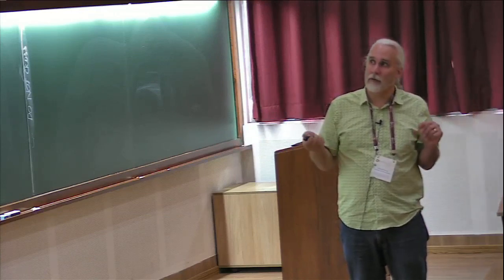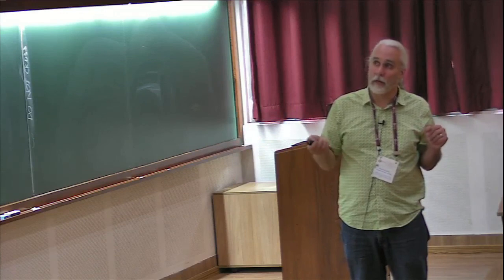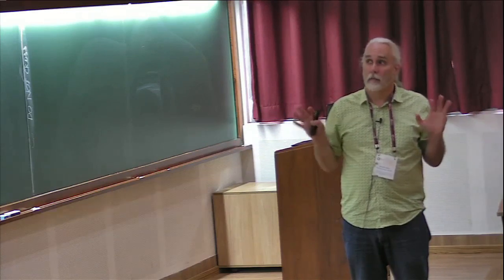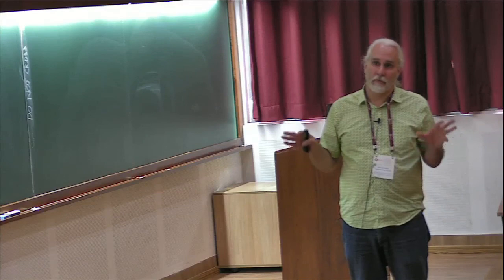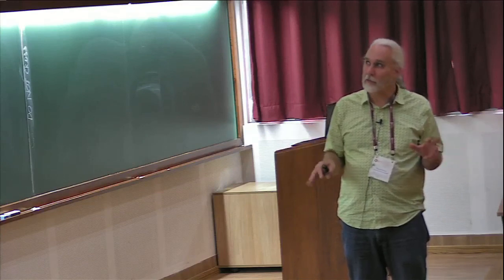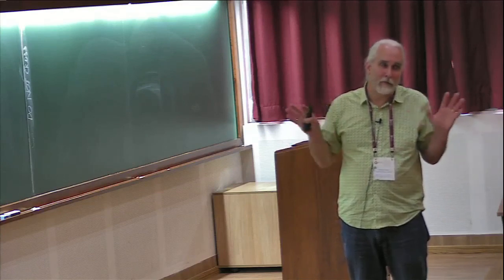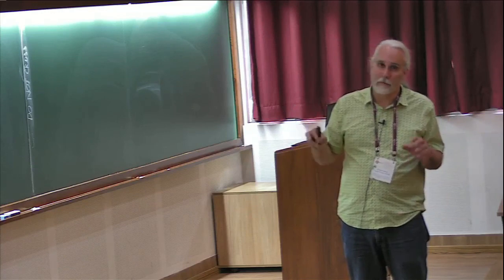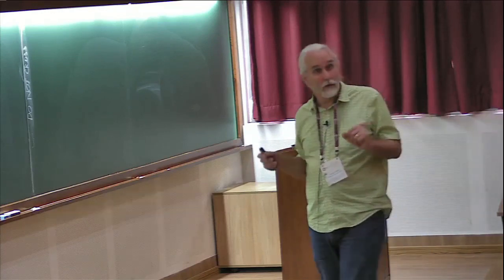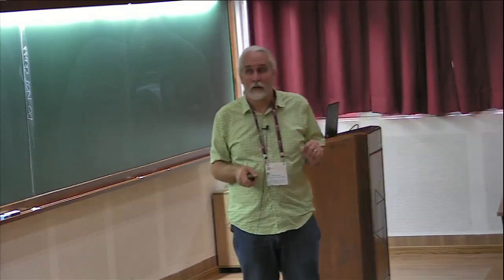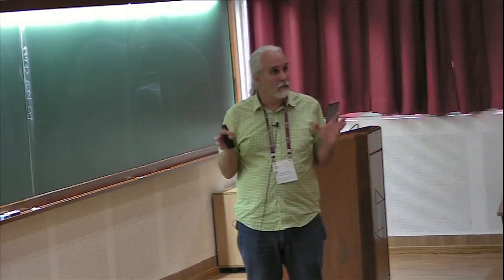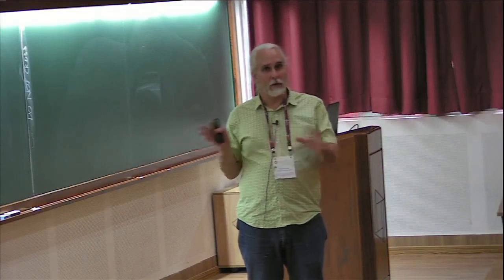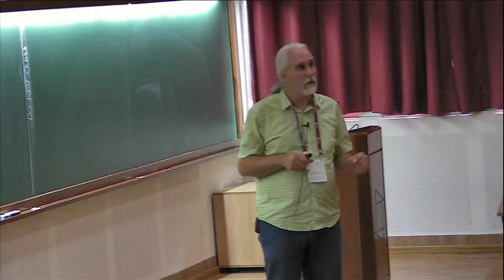It's actually much more disordered. The mobility is lower. It's only about 100 in this film, but it still shows perfect weak anti-localization. It means that you can still make this thing kind of disordered, and this Dirac cone behavior is still there, which I think is good. So we'd like to get the capping to work a little bit better so we don't make the films too disordered, but at least it's promising that we are able to do that transfer to a cryostat.